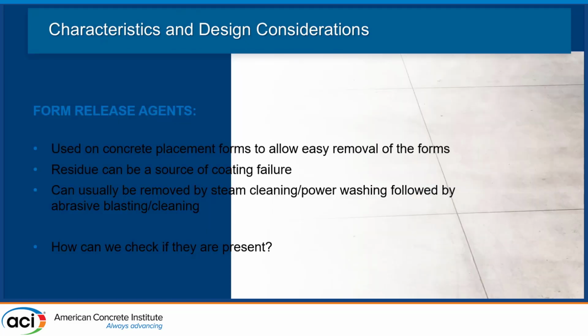And then form release agents. There are a lot of things added to the forms to aid in form release, but those can be surface contaminants that would inhibit the adhesion of a coating system on top of that. So any form release agents would need to be removed by pressure washing, water jetting, abrasive blasting, whatever the correct method based on that project would be, but those have to be removed. They would be considered surface contaminants before you apply the coating.